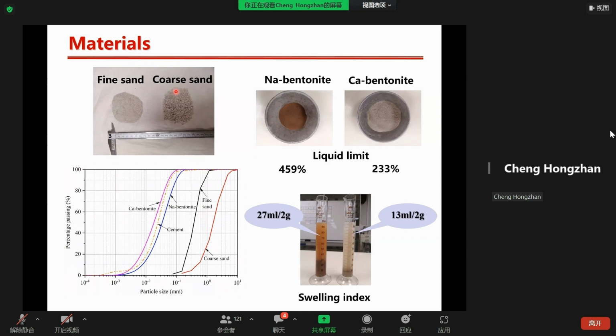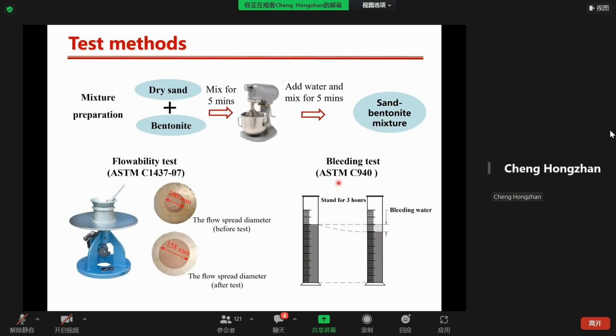The two bentonites were categorized as sodium bentonite and calcium bentonite. Based on their liquid limit and swelling index results, we can find that sodium bentonite has a much better water retention capacity and swelling potential. Okay, to prepare our sand bentonite mixture, the dry sand and the bentonite were first mixed in a mixer for 5 minutes, and clear water was added and mixed for another 5 minutes.